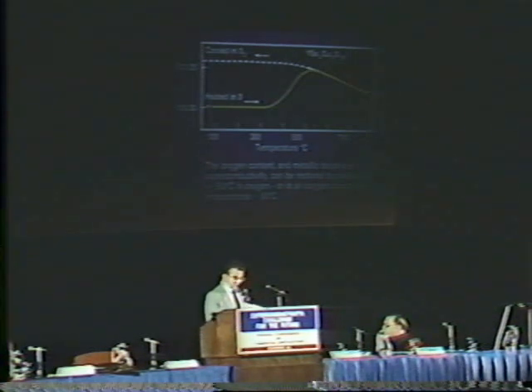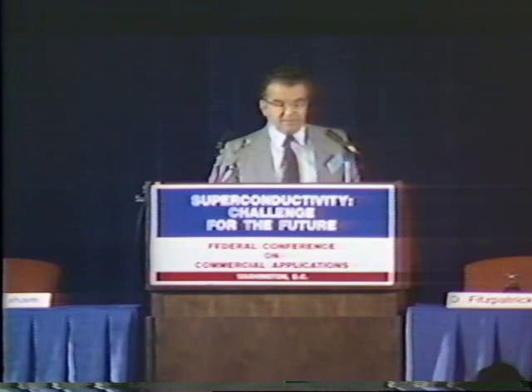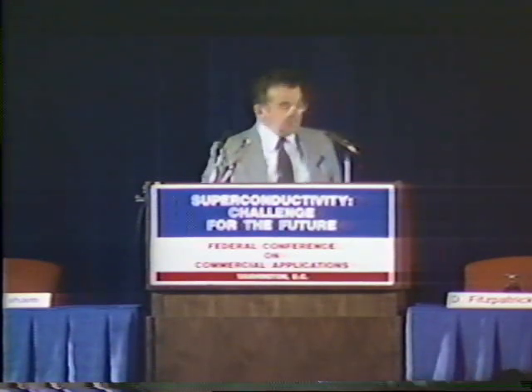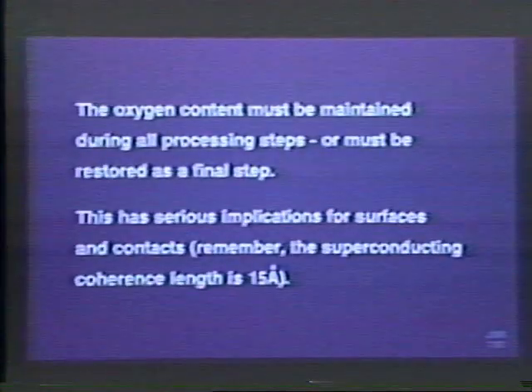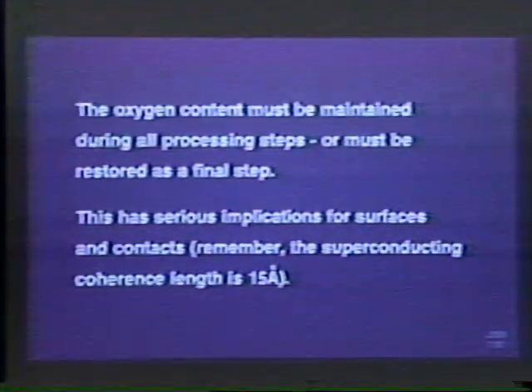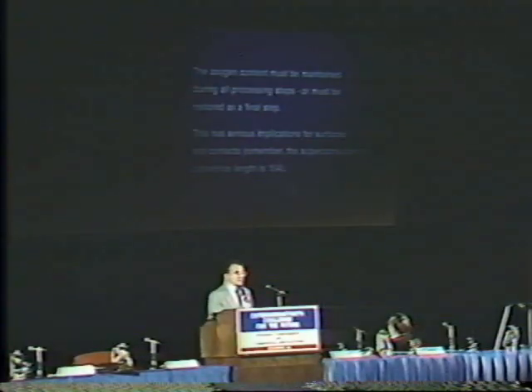So you can restore the superconductivity by this heating step. Let me summarize that. The next view graph, next slide. If you think about using this material in combination with others, what we can say is the oxygen content must be maintained during all processing steps, or if you lose it, it must be restored as a final step. And that's not so trivial if you think about a multi-level circuit. It introduces constraints that certainly don't exist with the old superconductors, don't exist with today's semiconductors.